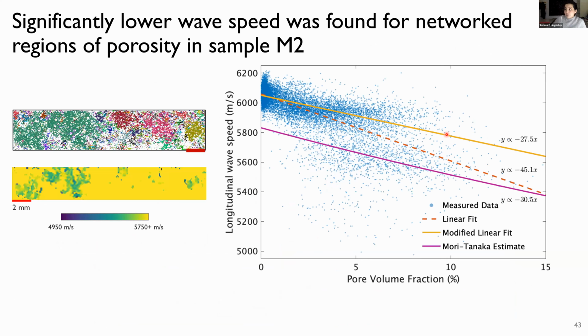So one of the things that we saw was that if we were to consider the spread of the wave speed, you see that there's a lot of scatter in this lower region. So essentially, if I were to draw a line just below here, the 6,000, and just consider the data that is falling outside of that, it's not really following much of a quasi-linear trend that you would expect from, say, a Mori-Tanaka or a Hashin-Shtrikman model, right? That's going to give you that quasi-linear relationship between wave speed and pore volume fraction.